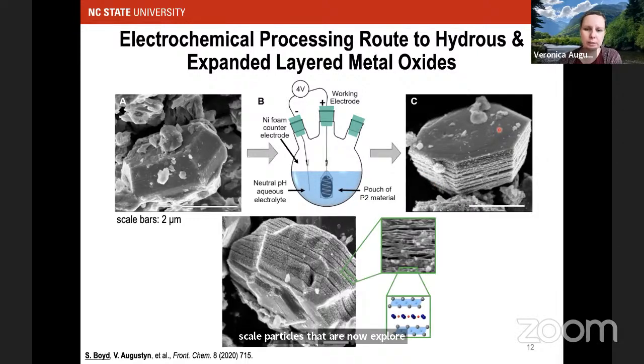So we decided to make lemonade out of a lemon, essentially, and say, okay, well, what if we do this process on powders of the material instead of on a slurry electrode, and try to make these expanded and hydrated metal oxides. So that's what we did. We placed a whole bunch of these P2 metal oxides into a pouch, apply a high voltage to drive sodium ions out of the material such that water will come in, and we form these beautiful micron scale particles that are now exfoliated and hydrated within their interlayer.